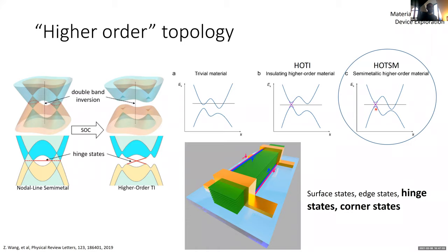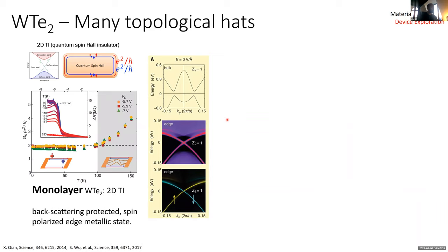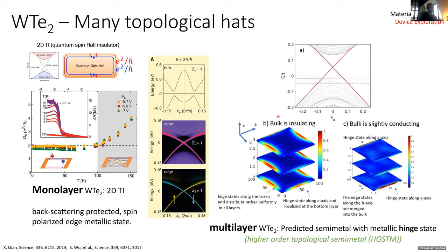so it's a semi-metal, but the Fermi level can't sit inside the entire gap. So WTe2, returning to that, it turns out over the years, since people have investigated so much and are still investigating it, it has many topological hats. In the monolayer, it loses a glide plane that it has in the multilayer that creates these Weyl points and all that. And it becomes a quantum spin Hall insulator that has been seen actually by Sanfeng, I think, when he was at MIT back in the day. It exhibits this quantum spin Hall insulator effect to very high temperatures. So that's very fun. In the multilayer, it was recently predicted that it should be a higher order topological semi-metal, that it should actually have hinge states as well.